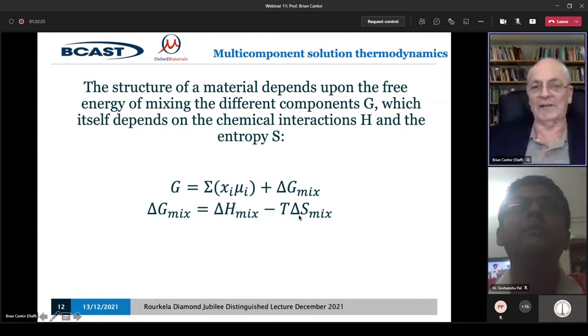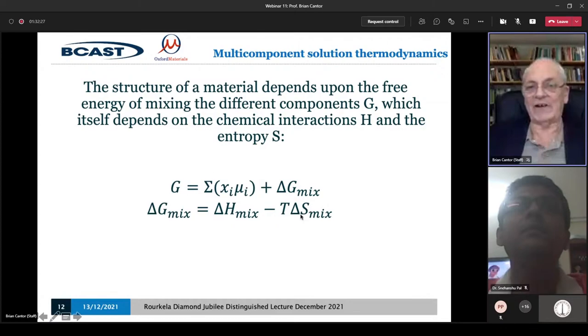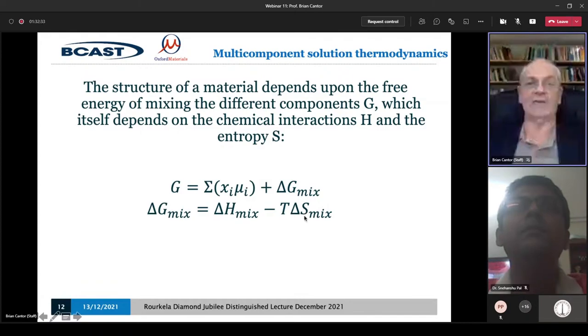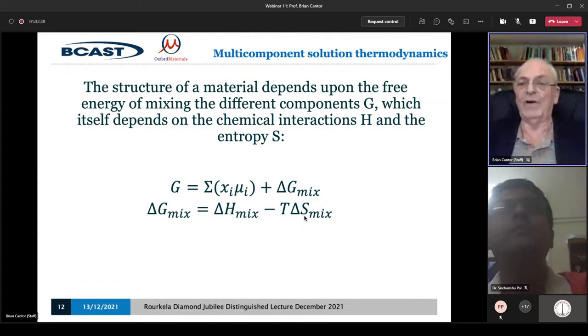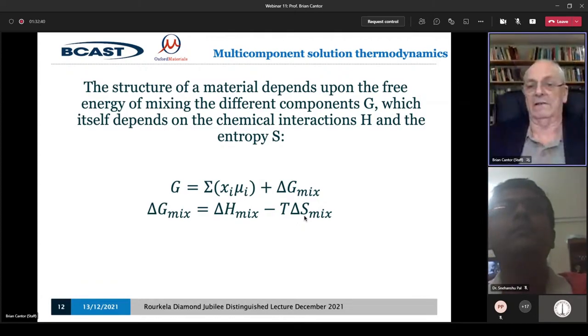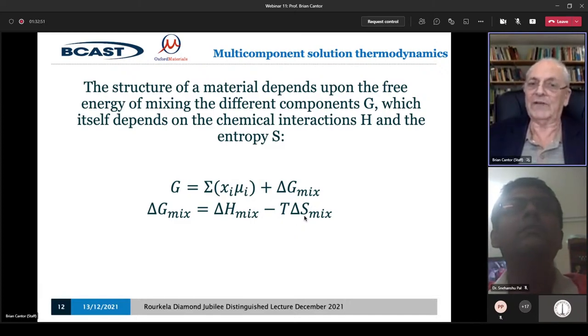Well, it's obvious actually, because the entropy effect goes to zero. And another definition of the so-called third law of thermodynamics is that at absolute zero, all materials are pure, perfect single crystals. It's got to be perfect single crystal, because you can't have any disorder, can't have any defects in it. And they've got to be pure, because if they're not pure, you've got random entropy because of the impurities. So at low temperatures, everything separates out.